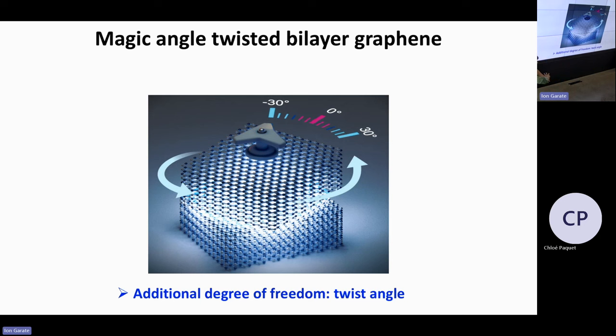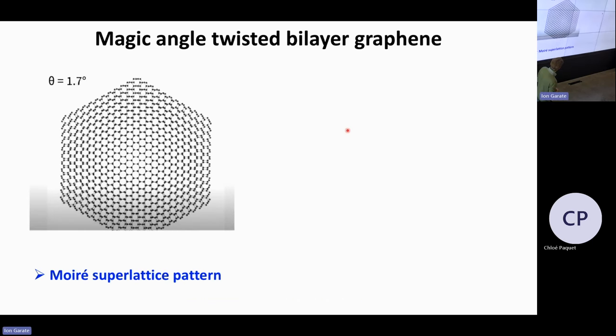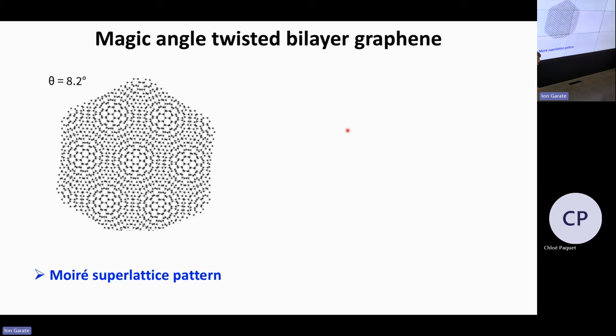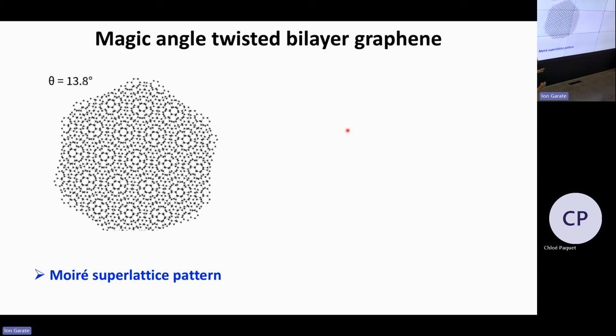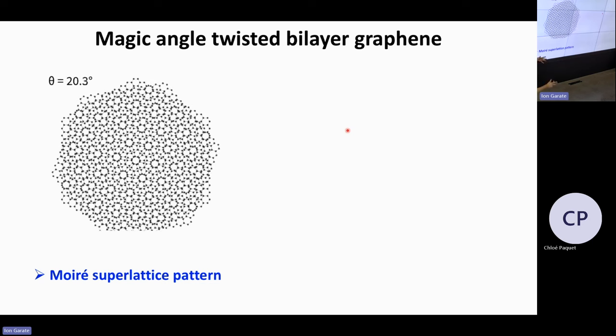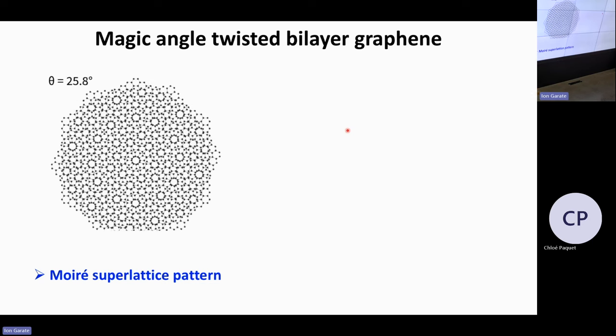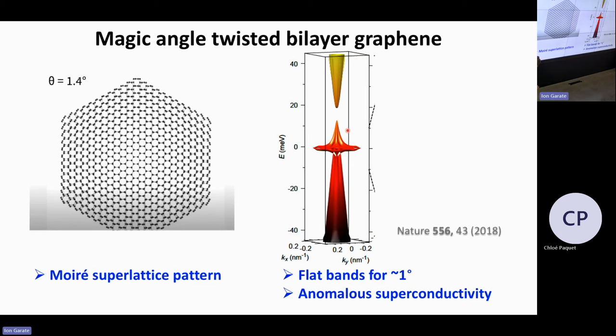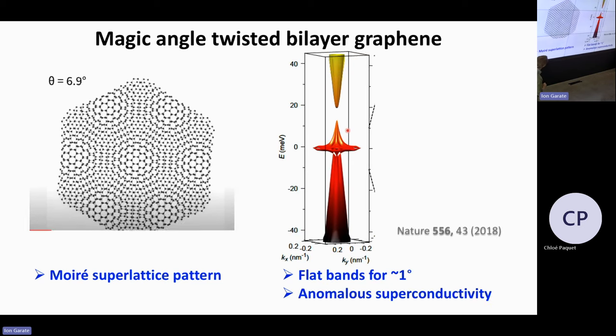Okay, so this is about magic angle twisted bilayer graphene. This is where you have this additional degree of freedom, where you twist, in this case, a single sheet of graphene on top of another single sheet of graphene. So it's two of the same flakes, but you change their angle. And what you then get is the formation of a moiré superlattice. You see that depending on the twist angle, you get periodicities that are either smaller or larger. Don't look at it for too long because you get a little bit dizzy. So I'll stop it soon.